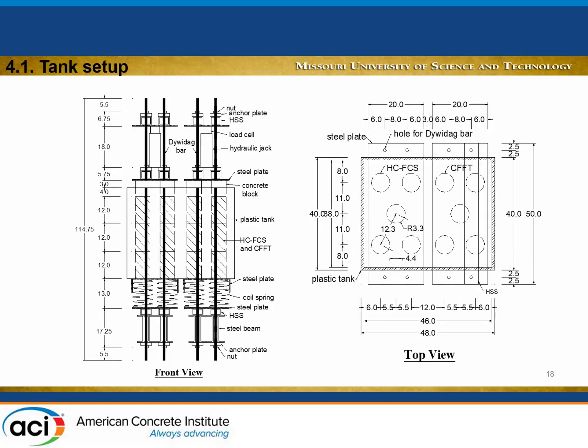So here is the test setup. For each tank, because it's the same temperature, we have five sets of specimens of concrete filled fiber tubes, and then on the same tank we have 5 sets of the hollow core fiber. Then we have a steel plate. We load using the Dywidag bars, and we have springs over here to ensure that the load is constant with time. And we have HSS over here where we can anchor the Dywidag bars. We have load cells and strain gauges on the Dywidag bars, and we regularly monitor the loads and the strains to ensure that they're constant during testing.